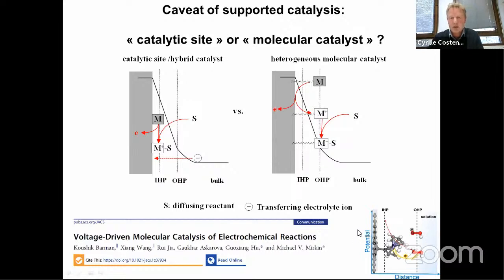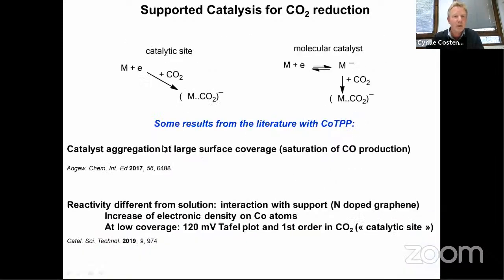And that would change the situation, because in this situation here, in absence of substrate, you do not see any current, because as you polarize the electrode, the electronic states of the catalyst are moving so that you do not trigger any electron transfer. You need the substrate to localize the electrons. And so I would like just to finish with that.